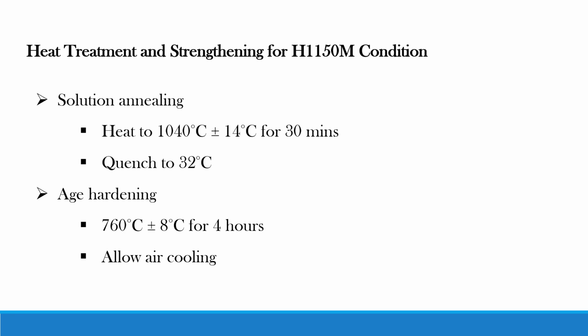H1150M condition involves solution annealing, age hardening, and air cooling, where the material is heated to bring out precipitates that act as obstructions to dislocation movement, thereby increasing the strength of the material. With the solutionizing stage, where we heat the material to a high temperature, the material should be heated to a temperature of around 1040 degrees Celsius, plus or minus 14 degrees Celsius, for 30 minutes.